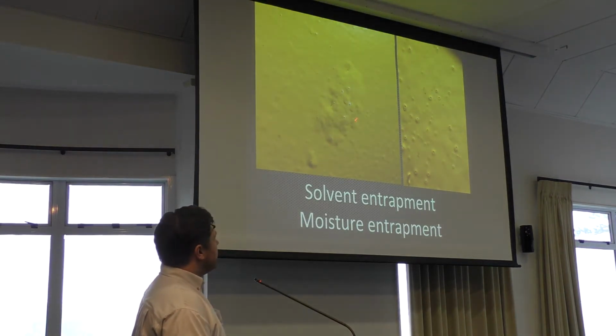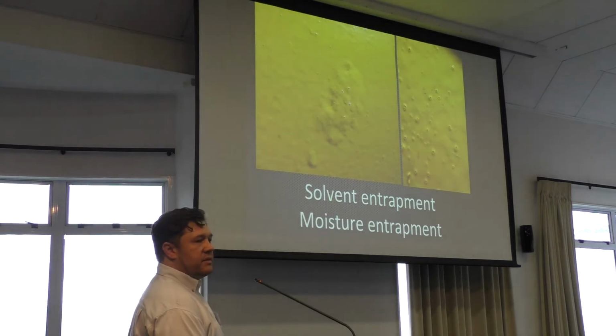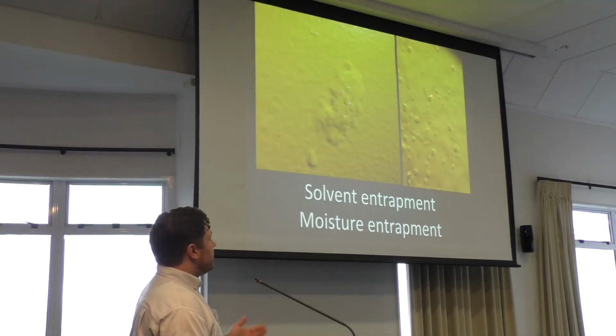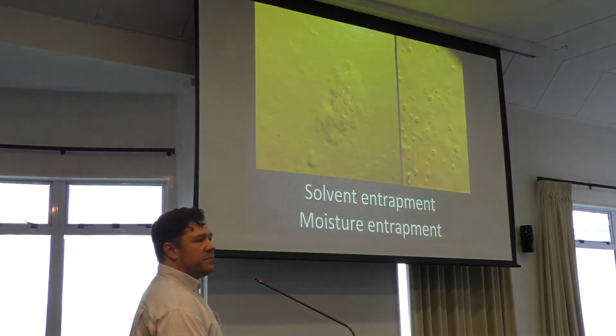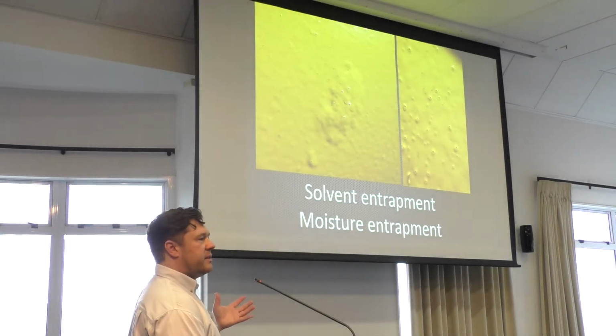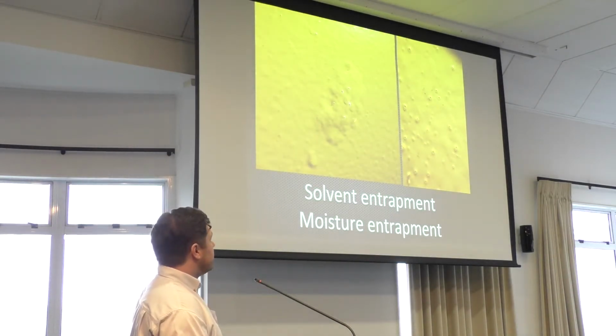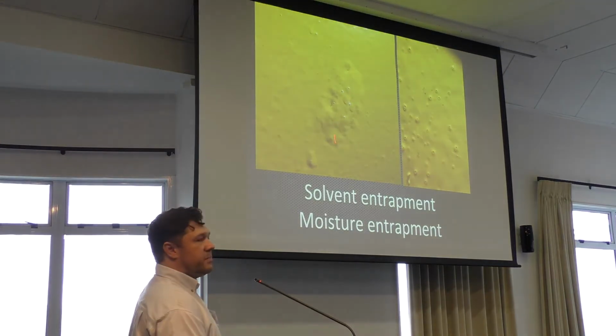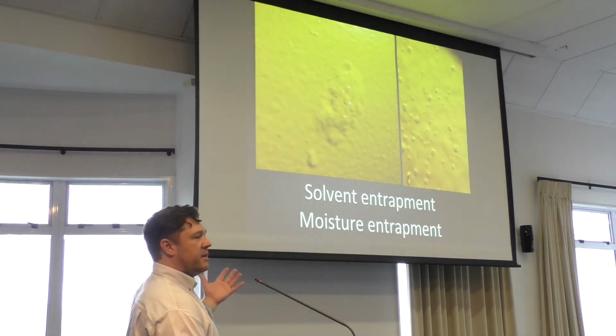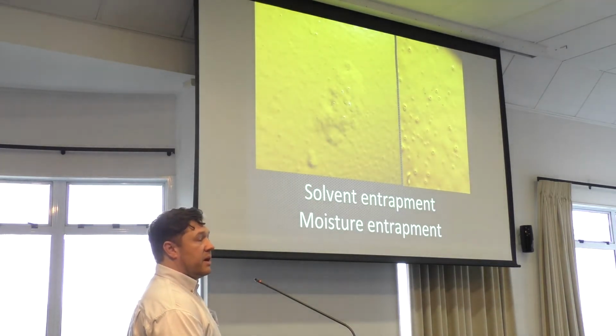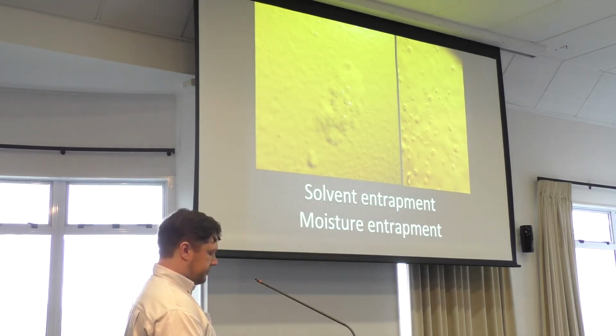You can see here that there's an activation of the zinc underneath the paint coating. So moisture has got through, maybe some pinholes that the bubbles left behind, and activated that zinc underneath your paint, which is then creating this white corrosion product, which is blistering your paint. And obviously spending the zinc in that area rather than over a general area. So you're going to end up with accelerated corrosion in that area.